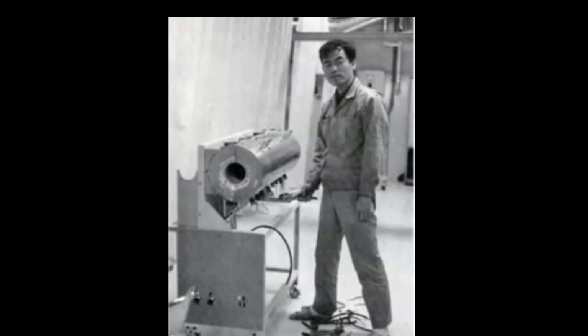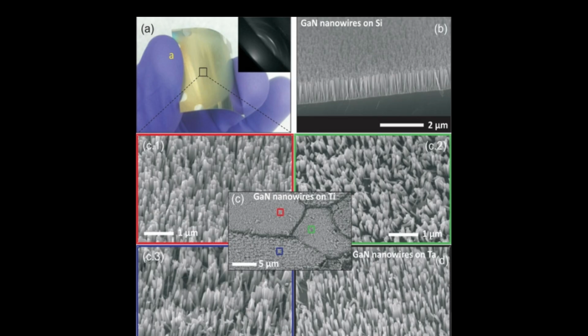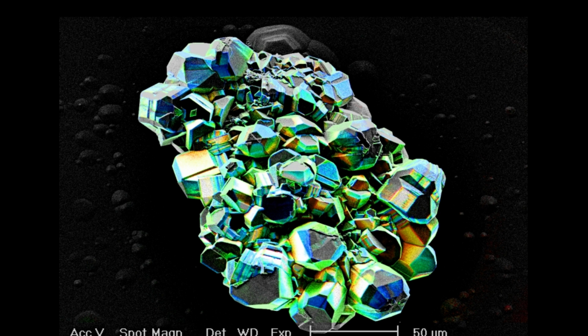But Nakamura had an advantage, his ability to customize his MOCVD reactor. This allowed him to use brute force, adjusting the reactor to pump as much indium as he could onto the gallium nitride, in the hopes that at least some would stick. To his surprise, the technique worked, giving him a clean indium gallium nitride crystal. He quickly incorporated this active layer into his LED.